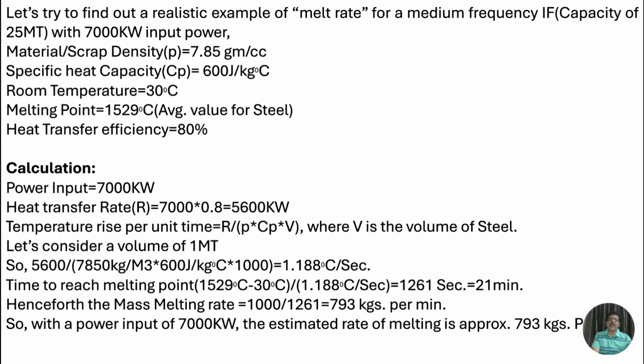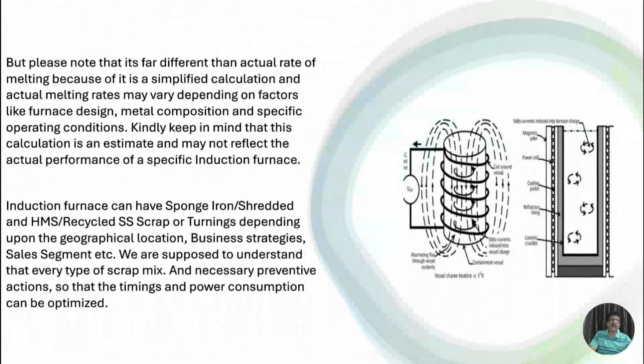Let's try to find a realistic example of melt rate for a medium frequency IF of 25 metric ton capacity with 7,000 kilowatt input power. The calculations are self-explanatory. With a power input of 7,000 kilowatt, the estimated rate of melting is approximately 793 kg per minute. But please note that it's far different from the actual rate of melting because it is a simplified calculation, and actual melting rates may vary depending on factors like furnace design, metal composition, and specific operating conditions.